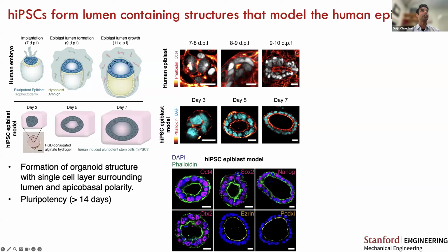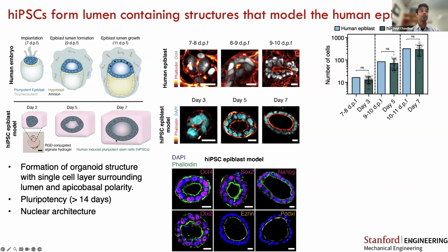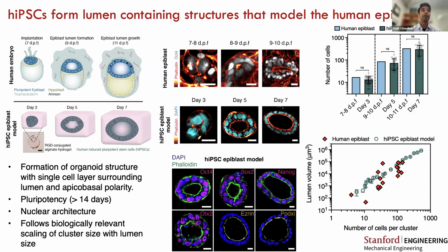And all of these features are what we see in our in vitro model, where the cells maintain their pluripotency. They have the single layer, and they exhibit apicobasal polarization. We also see some similarities in the nuclear architecture. The size of the nucleus and some features of the nucleus are similar between our in vitro model and in vivo, and closer than what we find from culturing these pluripotent stem cells in Matrigel, for example. And we also see the biologically relevant scaling between the number of cells and lumen volume and how rapidly these clusters expand. So for all of these reasons, we think that this epiblast-like structure that's forming in these hydrogels may serve as a nice model of the early human epiblast.